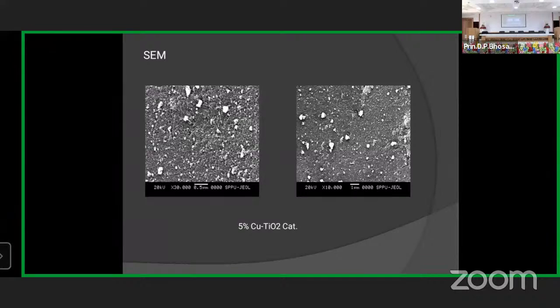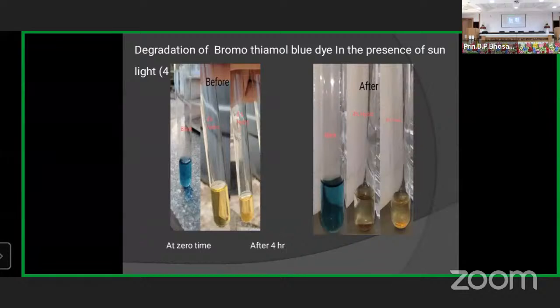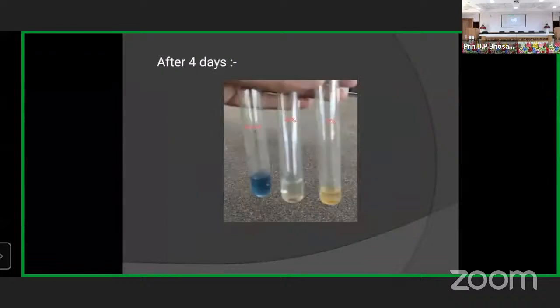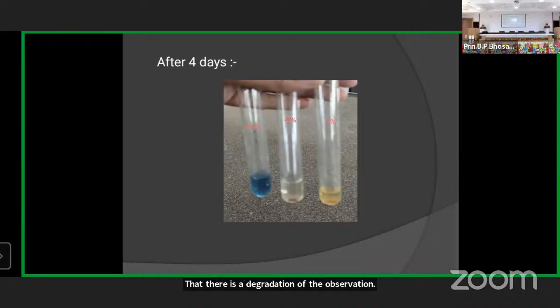Now this is the actual degradation of the dye. In the first picture, we see the state at time zero when we put in the catalyst. The first is blank, the second one uses the 4% catalyst, and the third is the 5% catalyst. After 4 hours, in the second picture, we see that the 4% test tube shows very faint color. After 4 days, we observe the same test tube, and the 4% test tube is more clear. It indicates that there is a degradation of the bromothymol blue.